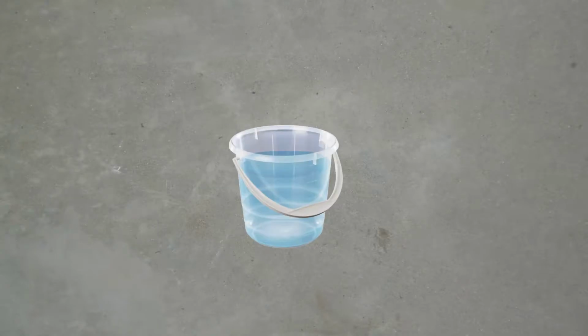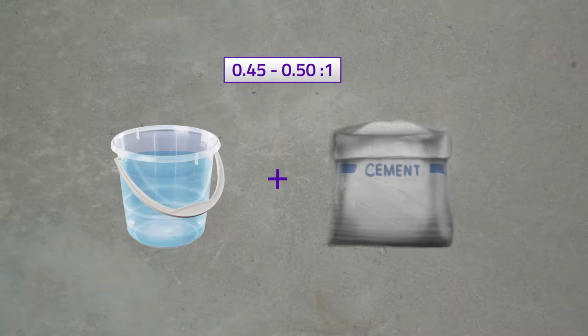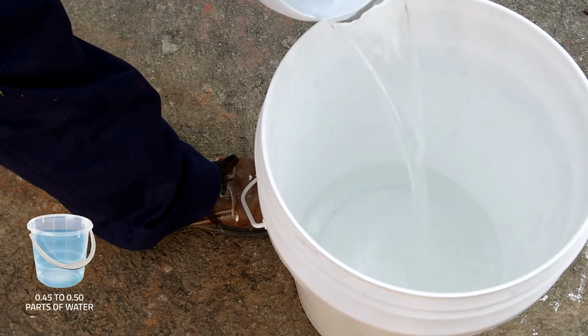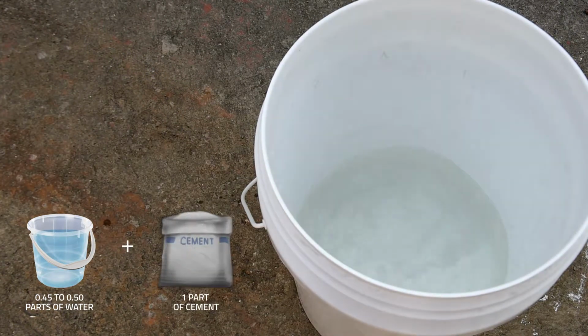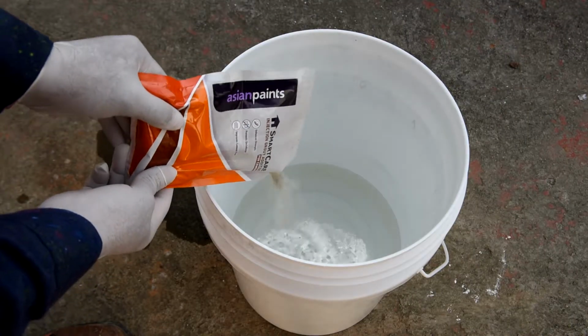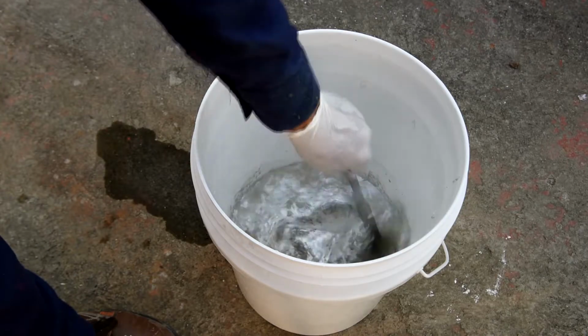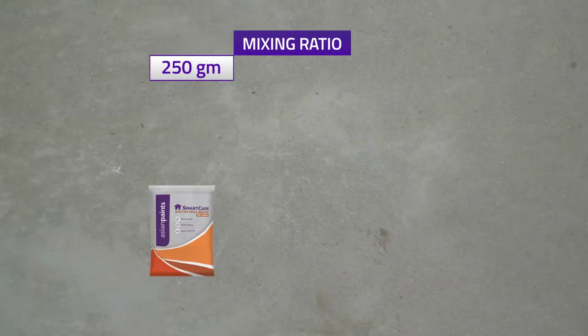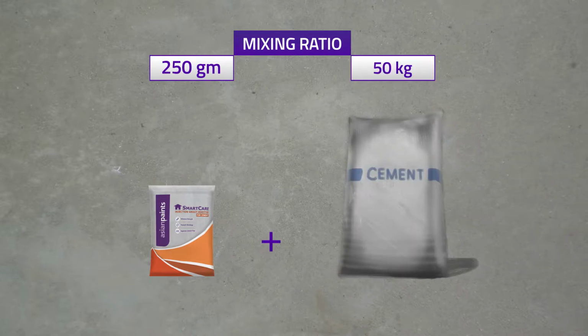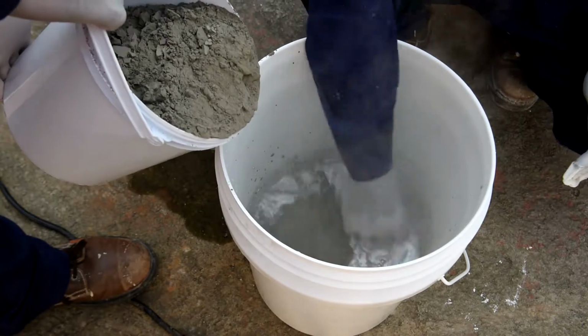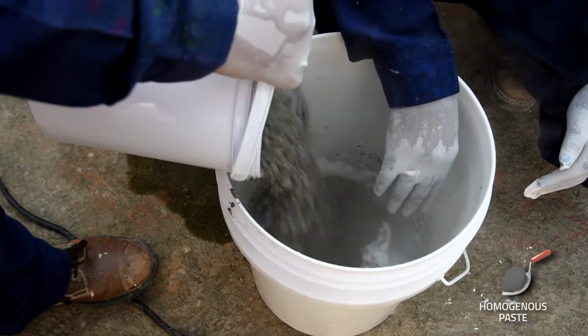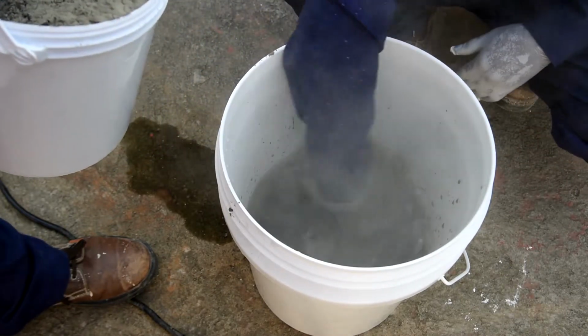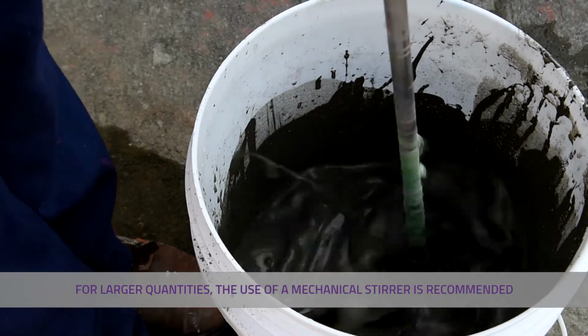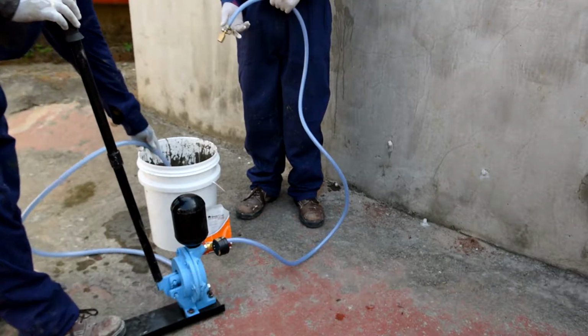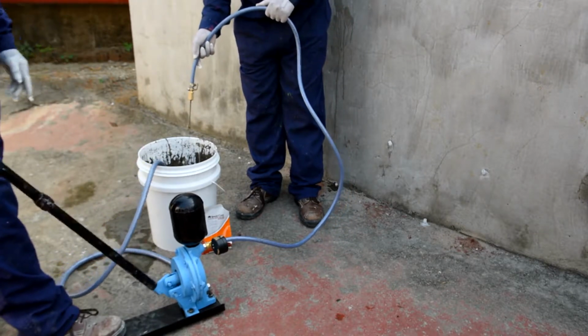Next, we can prepare the grouting mixture by pouring water in a clean bucket following a water to cement ratio of 0.45 to 0.5:1. That is 0.45 to 0.5 parts of water for every 1 part of cement. Add SmartCare injection grout additive for cement to this water and stir it well. 250 grams of SmartCare injection grout additive should be used for every 50 kilograms of cement. Now add cement slowly to this mixture with continuous stirring to get a smooth homogeneous paste that is free from lumps. For larger quantities, a mechanical stirrer can also be used. Now use a manual or electrically operated pump to pump the grout through the nozzles.